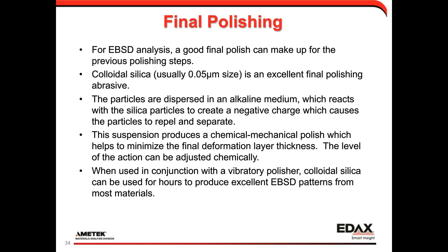One of the key points for EBSD is the final polishing step. My first bullet point here basically sums up a lot of the philosophy: a good final polish can make up for a lot of things going on in the previous polishing steps. And so the solution that's used and recommended is colloidal silica. And I've put here usually a 0.05 micron size. I'll give an example where we use a 0.02. I'd say usually 0.05 because it does pretty well and it's less expensive than the smaller abrasive. And it's a good polishing medium for EBSD.